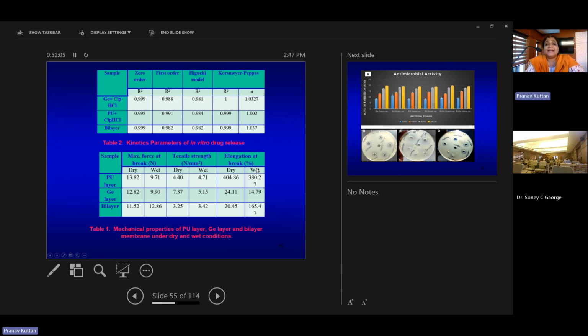And also, as I said, along with the degradation property, another important property is the mechanical strength. This membrane should have enough mechanical strength to act as a barrier. So different parameters like tensile strength and elongation at break, all the properties of the gelatin layer, polyurethane layer, and the bilayer were compared. We found some change in the elongation at break because, as we can see, the polyurethane layer in the dry condition is 404 and the gelatin layer is 24. But the bilayer is showing a value similar to gelatin.